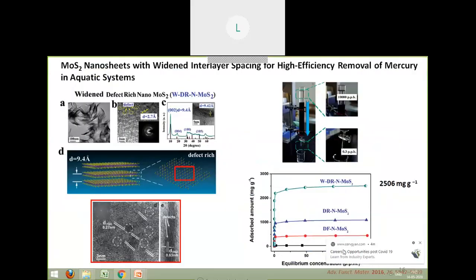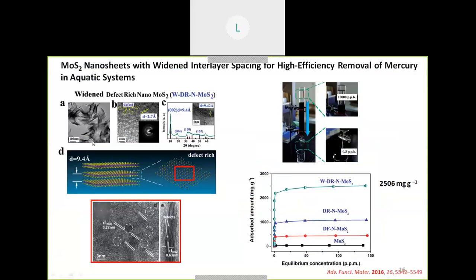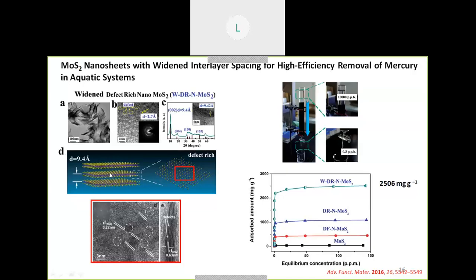So they have started studying this material. They knew the van der Waals forces are very weak, so they tried to separate the layers from each other. The surface area can be increased, or in other words, the inaccessible sulfide inside the layers can be made accessible for the pollutants. By increasing the amount of the reactant thiourea, they used a higher thiourea ratio and were able to create defects in the layer also.